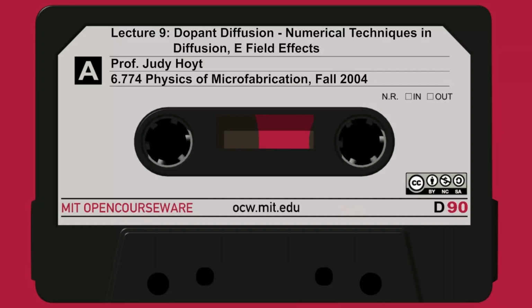Now, the equation in the center of the page can be simplified somewhat if we are in a special case where the diffusivity is a constant, where it doesn't vary in space. I can pull the D out of the partial derivative with respect to X, and we just get partial C partial T. So the time rate of change of the concentration is equal to a constant diffusivity, it's a number, times the second derivative of the concentration with respect to X. So that is, at the bottom of the page, the special case of Fick's second law when the diffusivity is a constant.